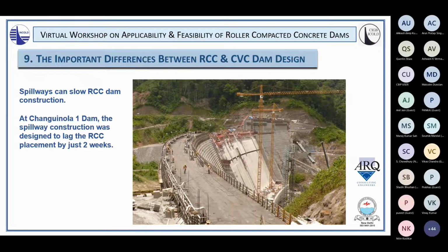And that may not be a problem in cases where you've got a dam that's going to take 1.5 years to fill, for example. But at the Changuinola 1 dam, which was filled from empty to full in 33 days, obviously it was very significant to ensure that the spillway was available immediately on completion of the structure. And consequently, the construction of the spillway was designed to lag the RCC placement by just 2 weeks. And consequently, there was no restriction. The spillway had no impact.